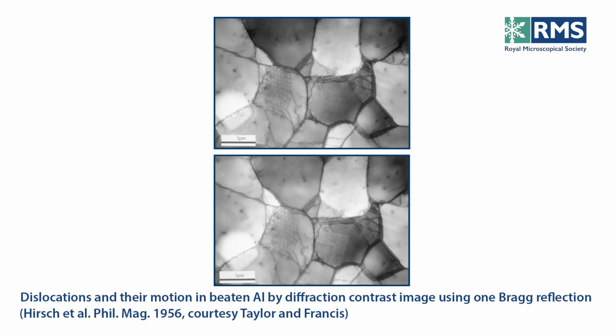It's called cross-slip, and that's an immediate validation, if you like, of one of the proposals made by the theoretical physicists that you'd get cross-slip, and here you are. Oh, so it had been predicted? Absolutely, it was predicted, and here you are, you can actually see it. And you can also see on this picture a cross-grid of dislocations, and that corresponds to a twist boundary parallel to the plane of the foil between two grains.